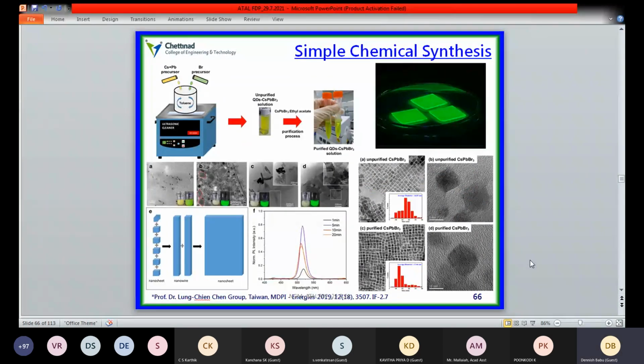We also used a simple ultrasonic cleaner methodology. We fabricated cesium lead bromide-based perovskite systems with the help of ultrasonic systems in the presence of ethyl acetate solution. We prepared some small nano rods, and those nano rods extend their shapes to nano sheets. These are platelets coated with these cesium lead bromide solutions by the spin coating method. Under the UV lamp, it glows green. These are the TEM images of the cesium lead bromide material prepared with the ultrasonic cleaner, showing very fine nano sheet-like structures.